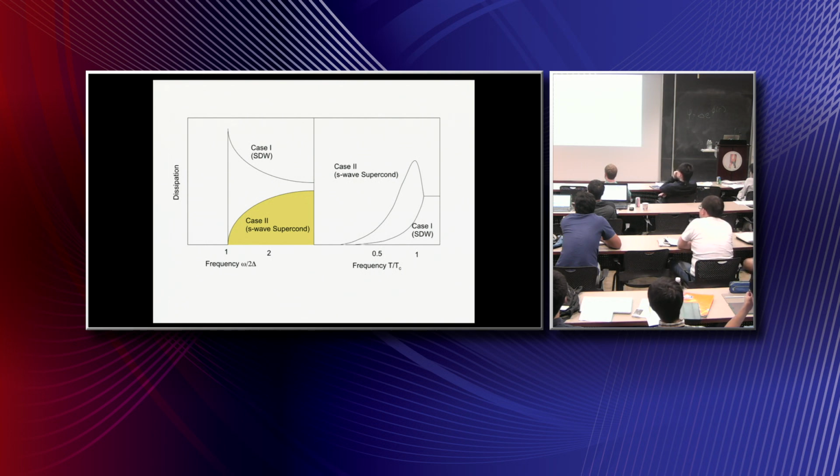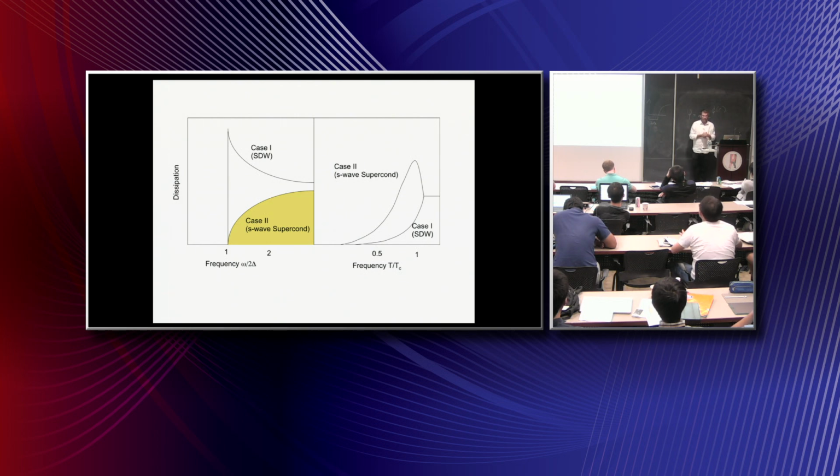That's not the whole story, of course, right? Because if you put enough energy in, we know superconductors are made up of Cooper pairs, and if we put enough energy in, we can break Cooper pairs apart. And so what we might imagine more generically is that a superconductor has a delta function, but then some energy scale, let's call it 2 delta, where delta is what we call the superconducting gap. This energy scale 2 delta is essentially the energy scale to break Cooper pairs out of the superconducting condensate. So this is in principle something that can be measured.